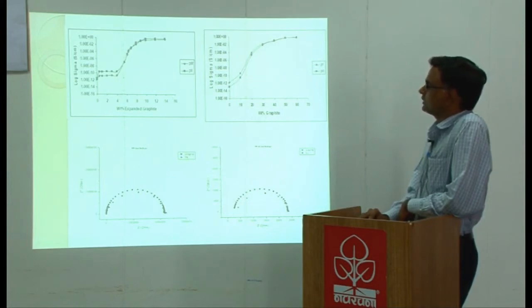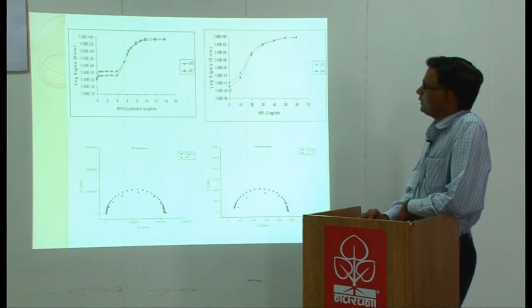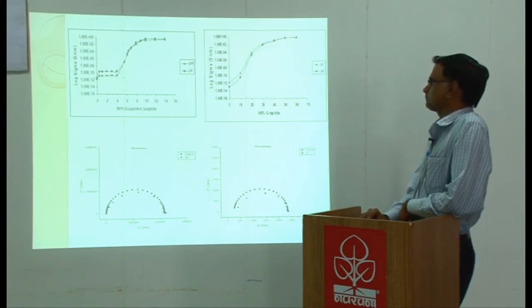I have just given it for comparison. You see that 5 micron graphite particles are added into the same PP matrix, and you make the composite in exactly the similar fashion, make pellets and measure the electrical resistance. You see that the electrical percolation is greater than 10%. So what we can understand from these two plots is that it is because of the formation of graphite nanosheets, which will be proved eventually in further slides, that the electrical percolation is reduced to a greater extent.